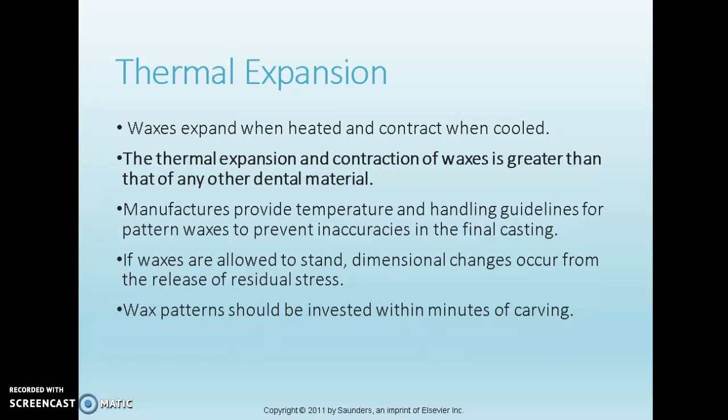As far as thermal expansion, we know that waxes expand when heated and contract when cooled. The thermal expansion and then contraction of waxes is greater than that of any other dental material. Please notice that that is bolded for you to remember. Manufacturers provide temperatures and handling guidelines for pattern waxes to prevent inaccuracies in the final casting that is created. If waxes are allowed to stand, dimensional changes occur from the release of residual stress. Wax patterns should be invested within just a few minutes of carving so that they do not distort.